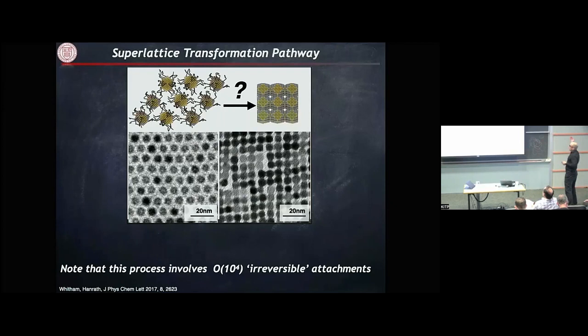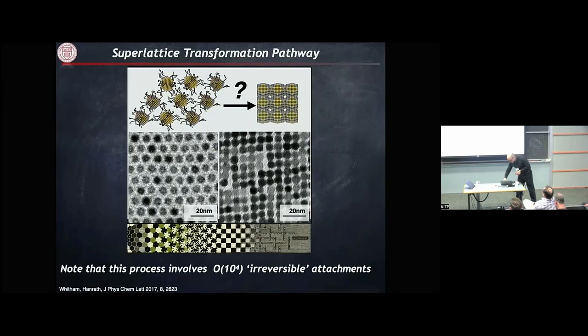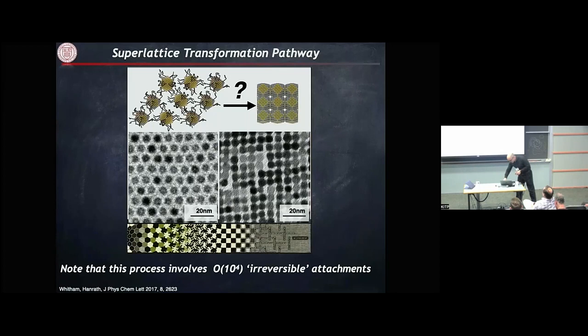What's interesting is that when you think about the initial stages during assembly, it's not actually a pristine fluid surface that you populate with colloidal suspension. You have this pre-nucleation layer and that impacts what sort of structure you form afterwards. That's an interesting insight from the in-situ studies and it informs this symmetry transformation inspired by Escher tessellations - going from a hexagonal structure of unconnected particles to a square structure of connected particles during the second stage of this process. You can put that on pretty Escher images, but if you think about it mechanistically, it's still amazing to think about. You have a system that has a lot of ligands on it, initially in one type of symmetry, and then they connect epitaxially. It's a process that involves tens of thousands or hundreds of thousands of irreversible attachments that are somehow orchestrated to give you superlattices that are not just tens of nanometers, but hundreds of nanometers and microns in length. It's not really well understood yet as to what really drives that, but I'll give you what we know at this stage.